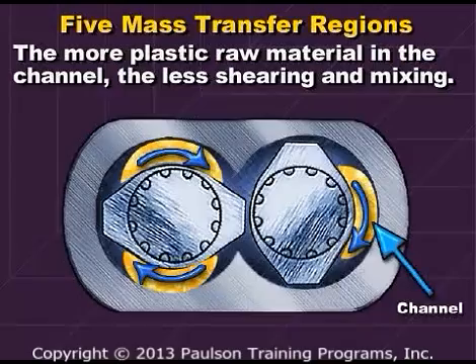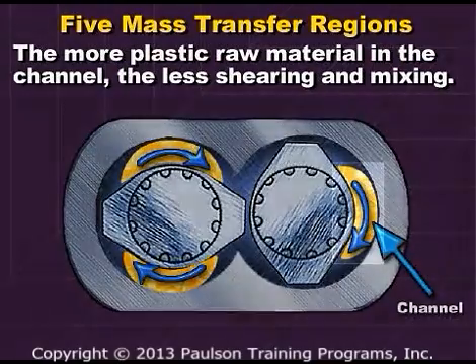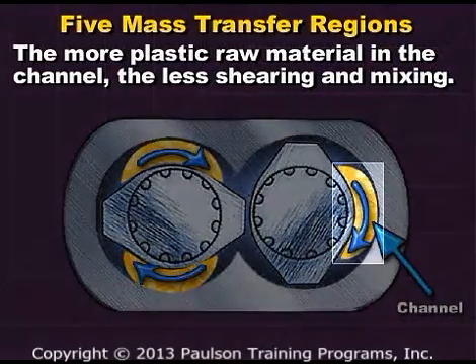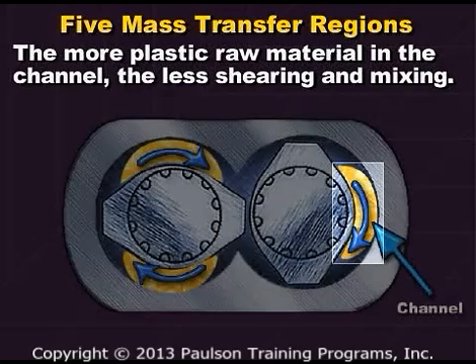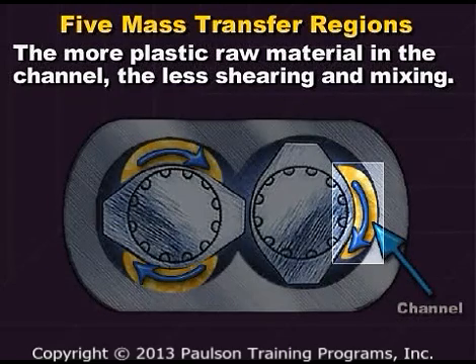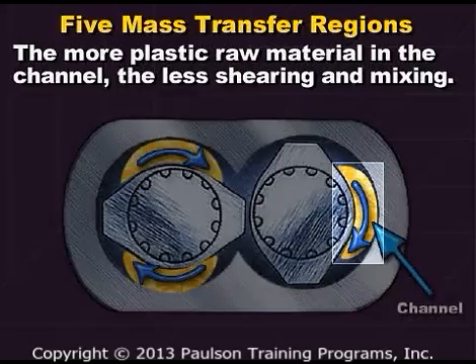Running the screws with more plastic raw material causes the screw channel region to be more filled. If there is more fill in the channel, there will be less shearing and mixing of the plastic.